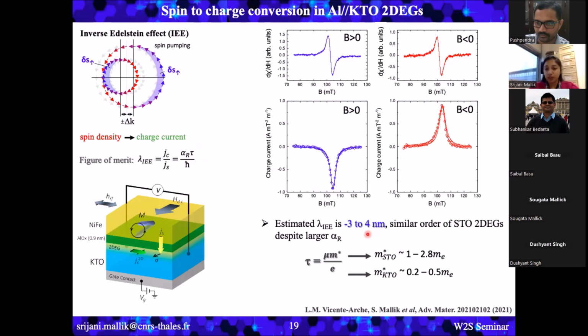Now the effective mass is a material property and we cannot change it. But what we can change is the mobility of our sample. I mentioned that in our samples, we got similar mobility for the STO 2DEGs and KTO 2DEGs. So as a future perspective, I would like to mention that we need to grow samples with much higher mobility so that we can really take advantage of this one order of magnitude higher Rashba spin orbit coupling to gain a lot in the lambda.